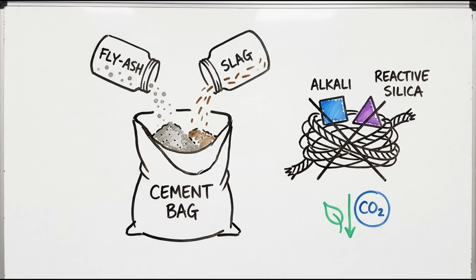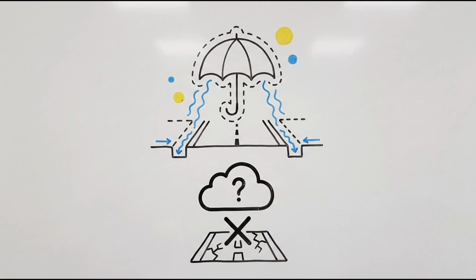Defense number 3, and this is the elegant one. Partially replace ordinary cement with supplementary materials like fly ash or ground granulated blast furnace slag. These byproduct materials chemically bind up free alkalis and reactive silica in a slower, more controlled, non-expansive way, essentially diffusing the reaction before it can build dangerous internal pressure. As a bonus, this also happens to reduce concrete's carbon footprint. Defense number 4. Limit moisture exposure where practical, since ASR needs water to proceed. Though, for something that sits outdoors and gets rained on for 30 years, this is more of a supporting strategy than a primary one.